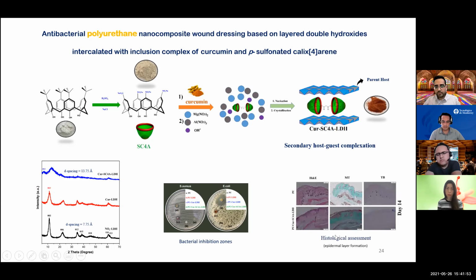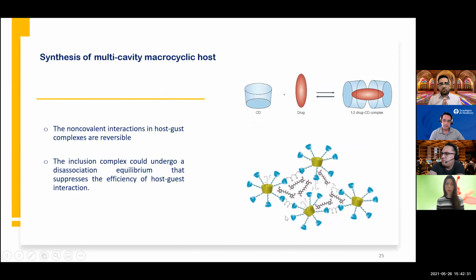The other thing that I want to mention is the histological assessment, because we did an in vivo test for these secondary host-guest complexations, and it's regarding the epidermal layer formation. And as you can see here, according to the H and E staining, we can see the formation of the epidermal layer, and also we can see a lot of hair follicles, and it shows that we have really nice healing in comparison with curcumin. The other thing that I want to mention is that